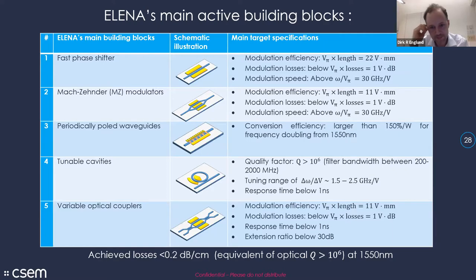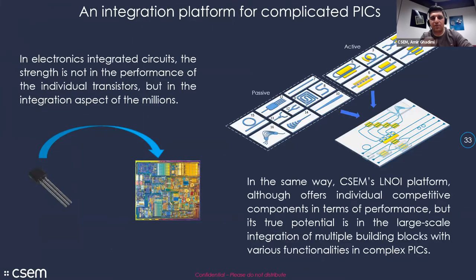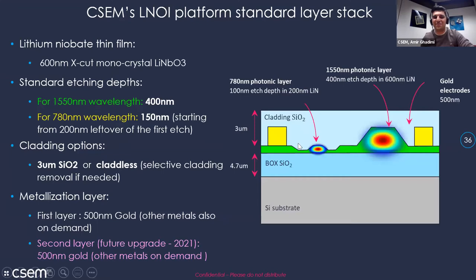The other thing that I can flash and advertise, Derek, especially motivated by your group: for people who are interested in accessing our foundry, maybe take a screenshot of this one slide. This shows our current stack layer, and coming back to phase matching from a different perspective, our standard stack is 600 nanometer X-cut lithium niobate on 4.7 micron of SiO2 on a silicon handle. Why 4.7? It seems to be the optimum thickness to achieve phase matching between RF and optics for high frequency modulation.